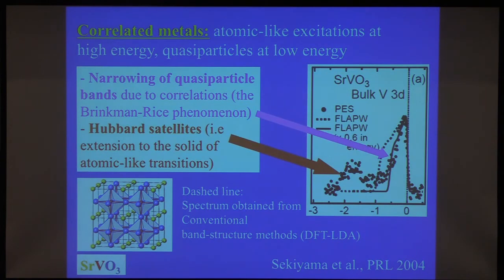So let me show you an example here. This is a material which may appear complex to some of you who are not condensed matter physicists, but for somebody like me, it is like the Drosophila of our field. It's a very simple transition metal oxide, and it's a metal. If you look at the excitation spectrum of this metal, as measured by photoemission, what you see here as a function of energy, this is the Fermi level, and this is below the Fermi level, occupied states. You see two kinds of excitations. Obviously, low energy excitations, which are the metallic quasi-particles, the delocalized aspect of the problem at low energy.